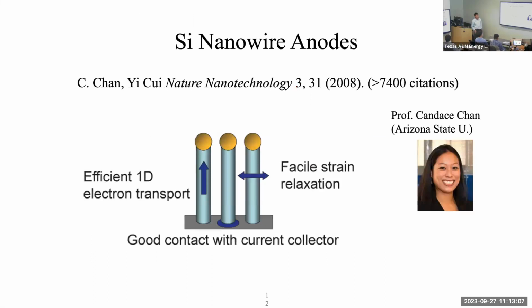I still remember when we published the first paper at the end of 2007, December, and it officially came out in 2008, January. This is a landmark paper in the battery field. How do we use nanoscience design to overcome the volume expansion problem? In this case, silicon nanowires grow directly onto a metallic current collector. Lithium can come in and go out from the sidewall of this nanowire. This nanowire is connected electronically and also mechanically with the underlying metallic foil. So the wire's diameter is small enough to relax the strain without breaking. Candace was my first graduate student actually working with me on this. After this paper, it really opened up the whole research field of nanoscience for battery research.